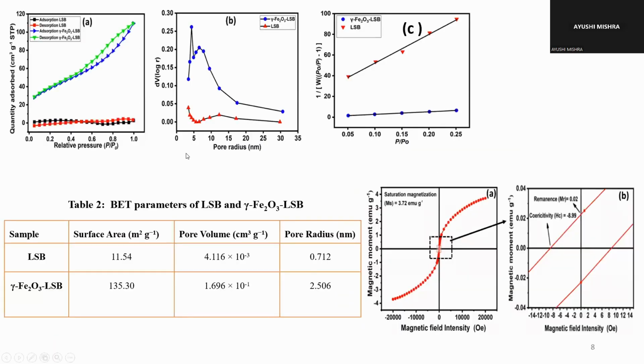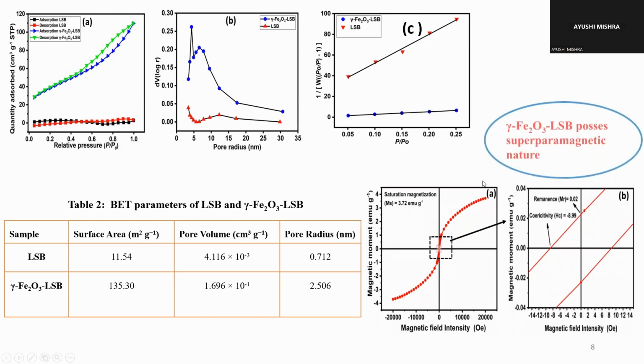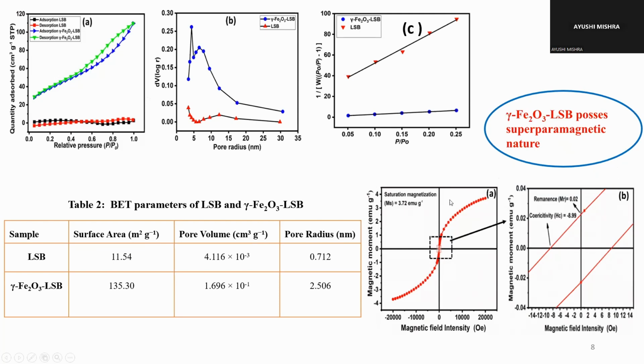And these are the BET spectra of biochar and magnetic biochar. We can see a huge change in the surface area of the magnetic biochar, which may be due to the increase of γ-Fe2O3 nanoparticles on the surface of the biochar. These are the VSM spectra, and the hysteresis curve shows the superparamagnetic nature of the magnetic biochar.